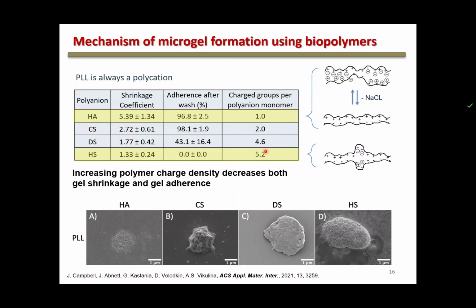And this is in inverse correlation with the charge density on polymer backbone. So we do believe that here, if there is stronger shrinkage, this is driven by annealing, and polymer can find the best spherical combination. This would compensate all possible charges or maximum of charges, and then if it's happening next to the solid surface, then not only electrostatic interaction, but hydrophobic interaction and maybe other short-range interactions are coming into play, and then it sticks, and it's really hard to get rid of.